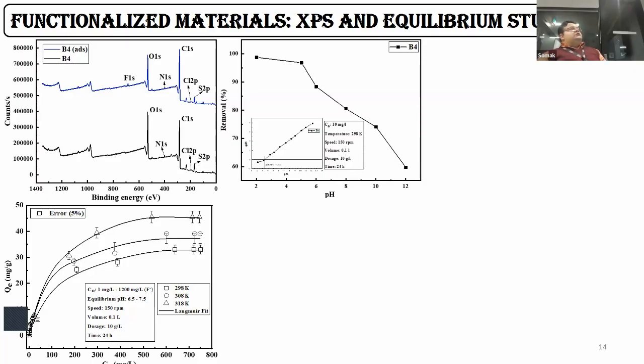Now coming on to the pH study. We did a pH study as well, and we can see that as the pH starts increasing, the removal percentage starts decreasing. The reason behind this is the isoelectric point of the beads is at 3.4. So when the pH is lesser than the pH ZPC (pH at the zero point charge), the surface of the bead is actually positive. Whereas if it is greater than this isoelectric point, the surface of the bead is actually negative.